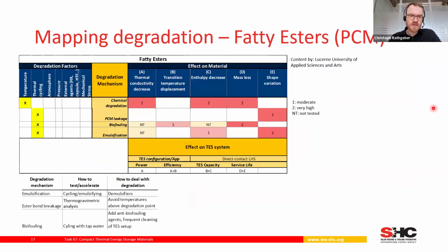Just to pick one, we have different degradation mechanisms that were tested for fatty esters here. One, for example, is the chemical degradation. So the first line, chemical degradation, depends mostly on the temperature. And if the chemical degradation occurs, then on material level, you will see a very high effect on thermal conductivity, on the enthalpy, and you will observe a mass loss. And now you see these different effects on material level.